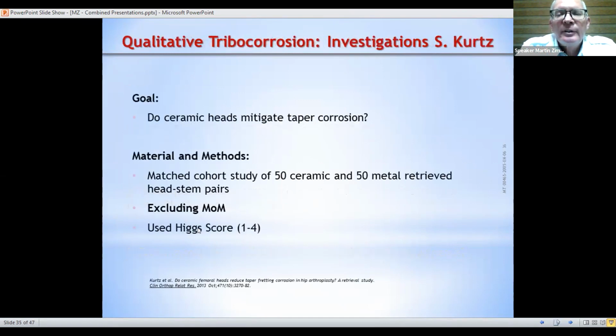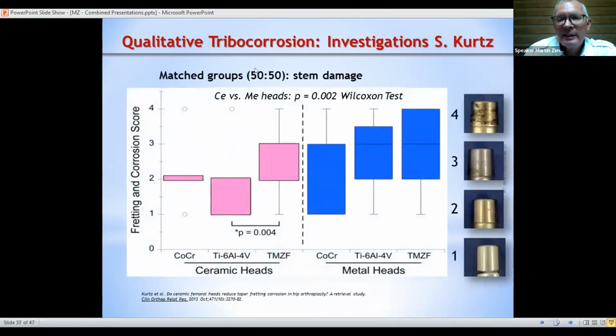To do that, we have a study from Steve Kurtz from America, which is based on a match cohort study of 50 ceramic and 50 metallic retrieved head-stem pairs. They excluded metal on metal, and they used a score noted 1 to 4 as a qualitative assessment. What is this qualitative assessment? You can see that on the right-hand side. Score number 1, no fretting corrosion; 2, mild fretting corrosion; 3, moderate; and 4, severe.